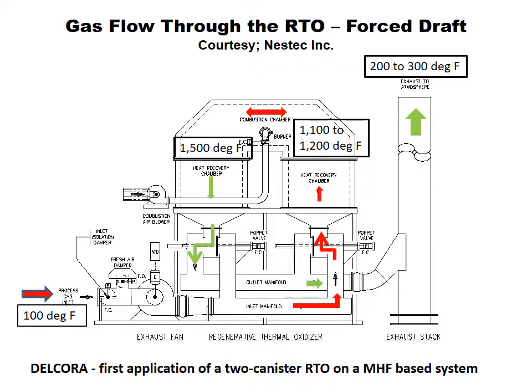This has been done before, but it's the first time anybody ever used a 2 canister RTO. They always use 3 canister. So what happens is the cool gases come in at about 100 degrees. They go through here, and there are these poppet valves. When the valve is in this position, the gases are directed up through the ceramic media. The temperature is elevated from 100 up to about 1100, 1200. There's a burner here. We operate this one at 1500.